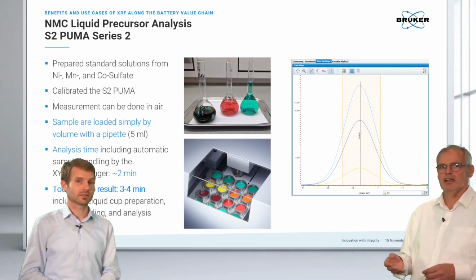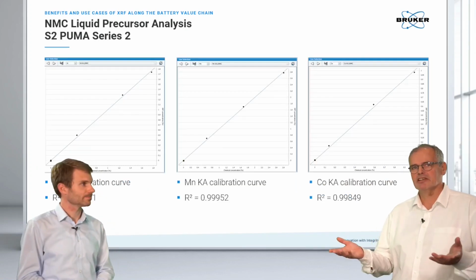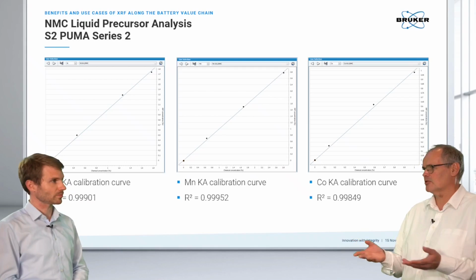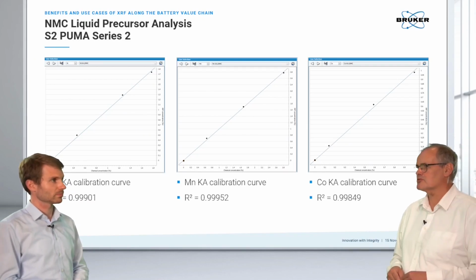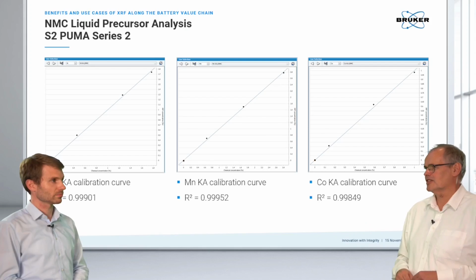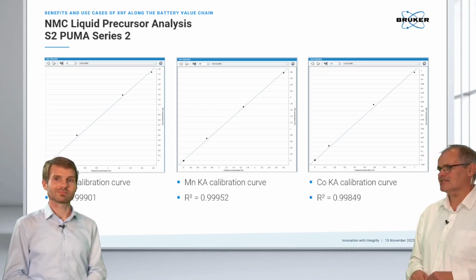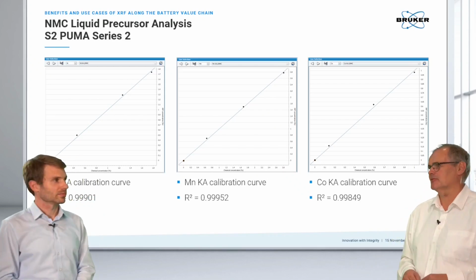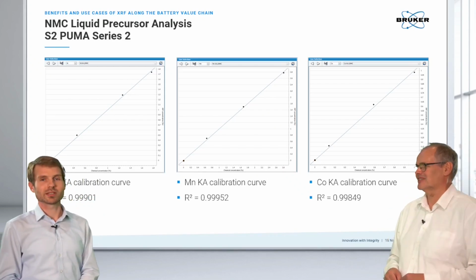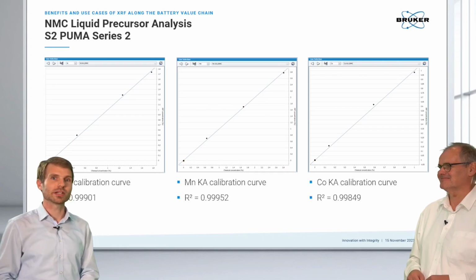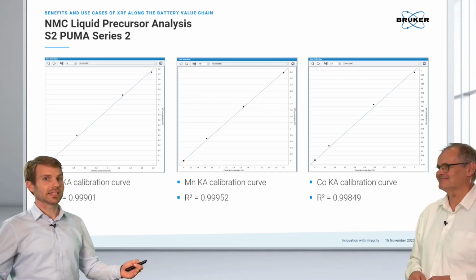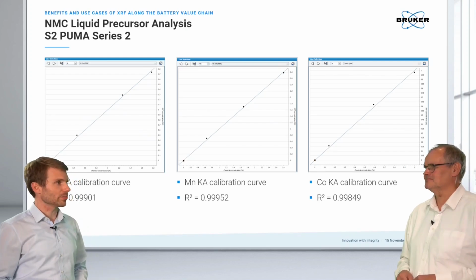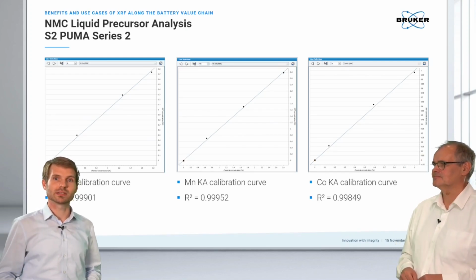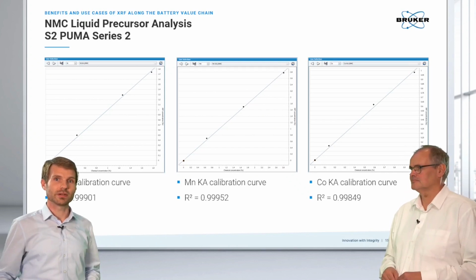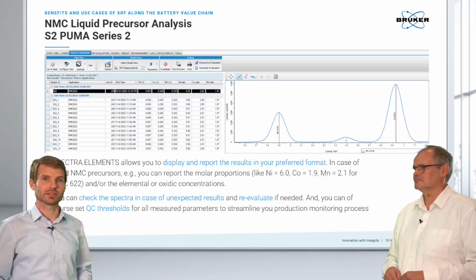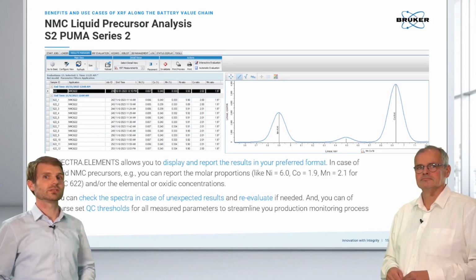Actually, when we see here the calibration curves are straight, it shows it's a straightforward process, and we see the correlation coefficient is close to 1. I guess it's a no-brainer. XRF can be calibrated and can be very accurate. These are the calibration curves here for the 3 elements. In this case, we just focus on the majors. Of course, we can also calibrate the traces and contaminants in the system and achieve a very good calibration curve and precision. And one brief look into our software here.